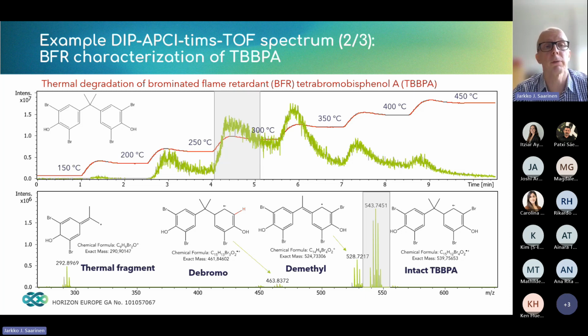So going from 150 to 450, and then here's an example around 300 degrees. What are the typical mass spectra that we get out of the TBBPA? So what we have here is that at 543, we have the intact TBBPA that is emitted, and then we also have the different components. There is a debromo and dimethyl components, and also the thermal fragments that are emitted as the TBBPA starts to degrade at 300 centigrade.